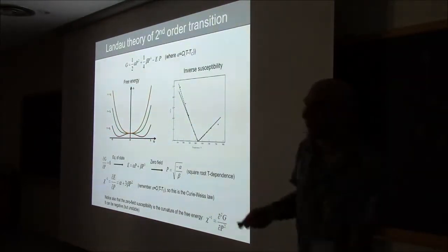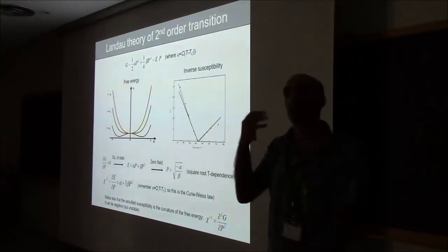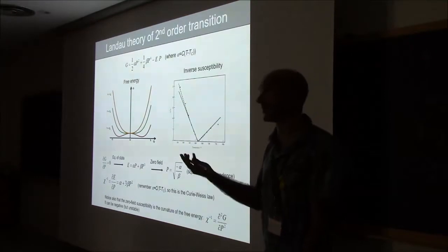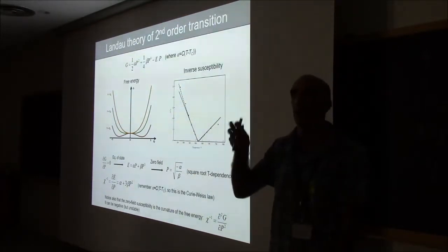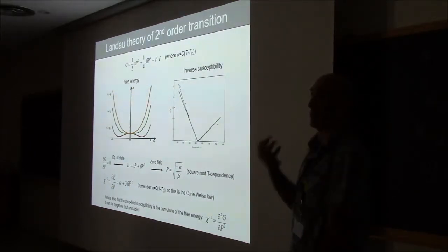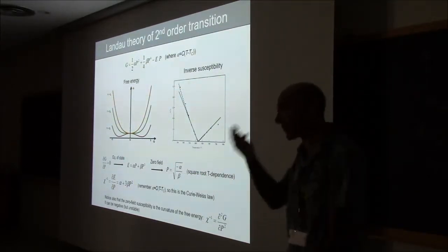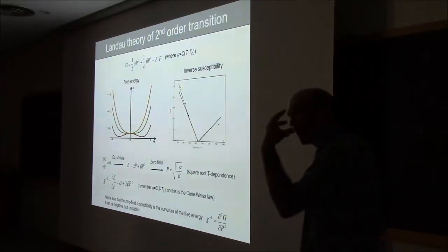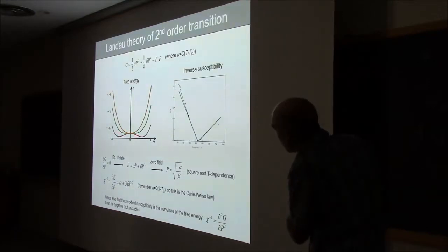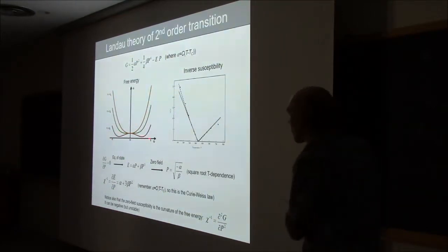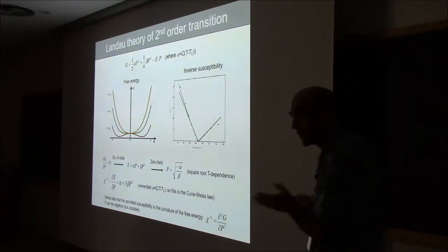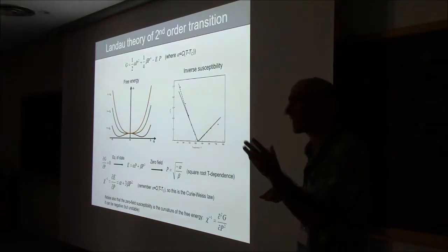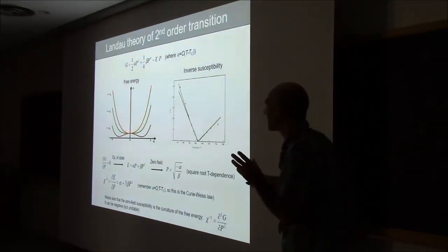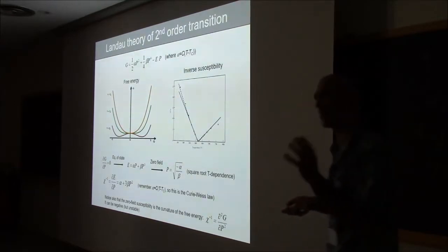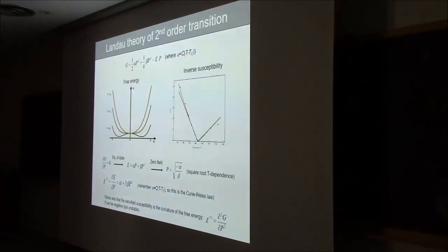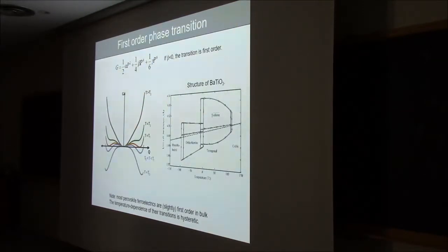The curvature here is positive, here is negative. I mention this because this is something that is becoming very fashionable right now, called negative capacitance. The physics of negative capacitance is more complex than I can even understand fully myself, never mind explain. But from a mathematical point of view, if you were sitting here, you would be operating in a landscape where the capacitance, or the dielectric constant, is negative. Of course you cannot sit here, being here is unstable, the stable states are this and this, but at least in a transient way you can be in a negative capacitance state. Nobody has killed me yet for saying that.